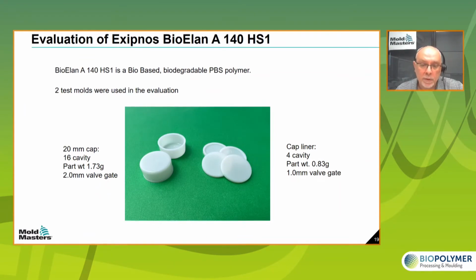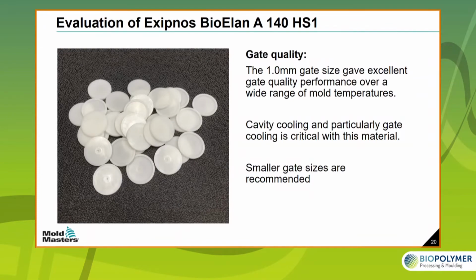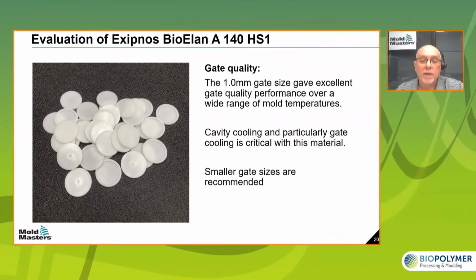It's a 4 cavity mold, so a smaller shot size, smaller part weight. It has a 1 millimeter gate. So we used both of these materials to evaluate the BioElan A140 material. First of all, the 4 cavity with the 1 millimeter gate gave us excellent gate quality. It has a thinner wall section, under 1 millimeter.